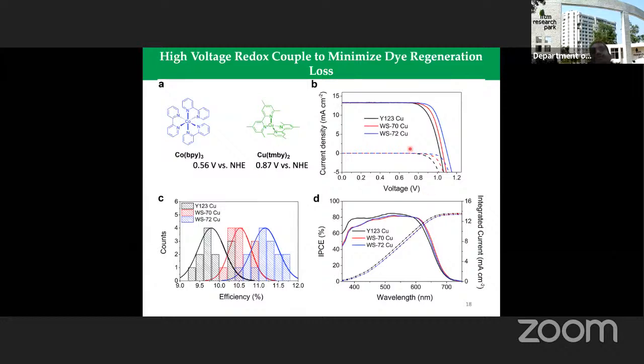So you can see here the corresponding IV curve. You can see as you modify from Y123 quinoxaline modified dyes, there is an increase in open circuit potential. That's what we need clearly. So what we have done, we have put quinoxaline and brought down the LUMO close to the conduction band. So we reduced one over potential, and then we manipulated your electrolyte and brought the redox energy close to the HOMO of the dye. Another over potential is controlled. So therefore, you have increased the open circuit potential. That is what you should keep in mind.